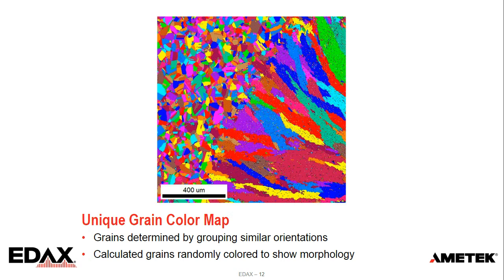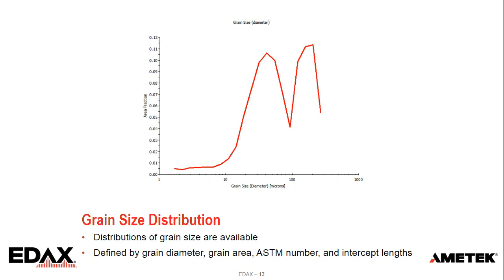And of course, if we know what the grains are in terms of pixels, we can figure out a grain size distribution that's shown here. We can define this grain size distribution a number of ways. I think the default often that people think about is in terms of diameter. That's an easy one to get out. That's the default, to show diameter. But of course, as we look at some of these grains and grain shapes, diameter doesn't always make sense when they're non-equiaxed grains. So we can do grain area. We can do ASTM numbers. We can do intercept length. There's a number of different ways of representing grain size that can be applied to the particular microstructure.